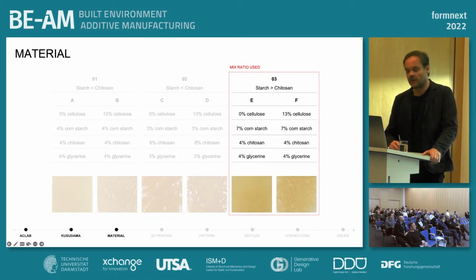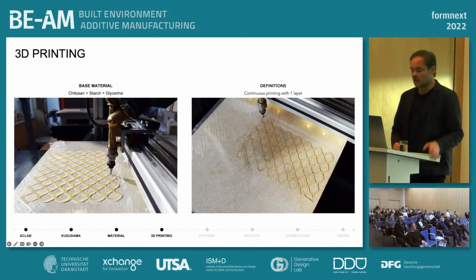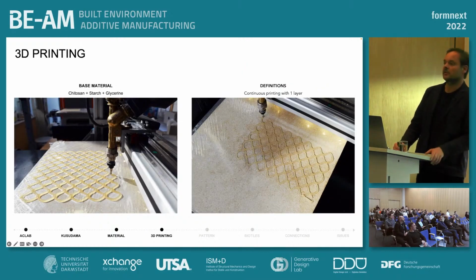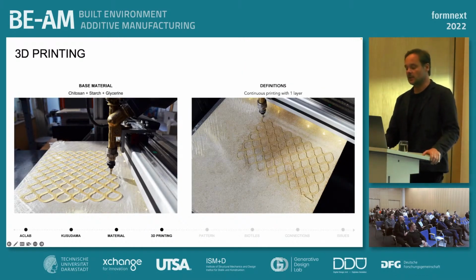If compared with the behavior of, for instance, group 2, with a higher amount of chitosan, it gets too hard to start printing and even to pour in a mold as a manufacturing process. So then we start doing the first set of tests. We start by defining grids and trying different mixtures based on chitosan, starch, and glycerin.